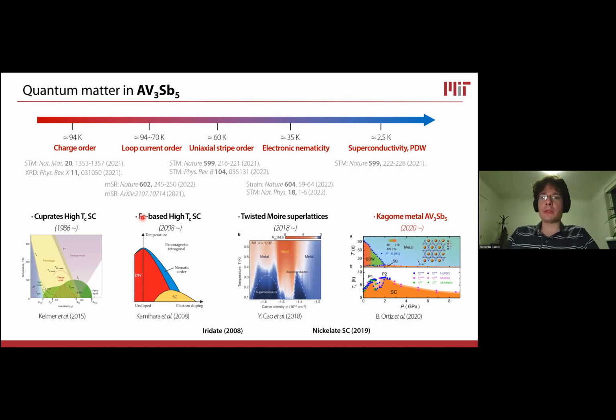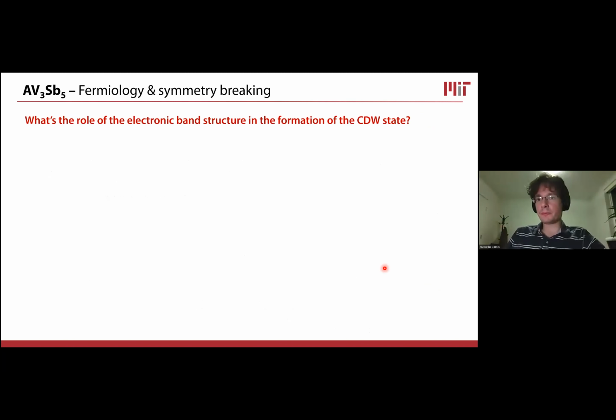So the cuprates, iron-based superconductors, and magic angle twisted bilayer graphene. What we can see in these Kagome metals is a competition between the charge density wave and superconductivity, which was proven with pressure studies, where you can enhance the superconductivity and get multiple domes of superconductivity concurrently with the suppression of the charge density wave. So there's a lot of physics involving symmetry breaking and competition between different phases.